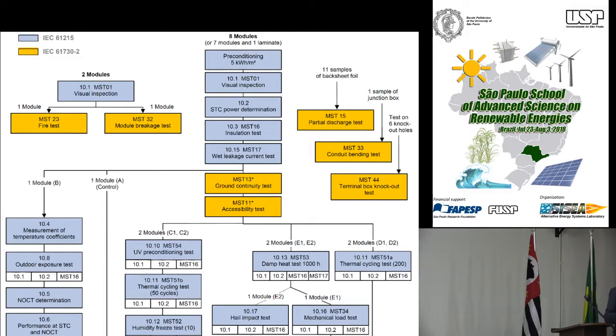That means we apply an irradiance value of 1000 watt per square meter on the module perpendicular. We make sure that the operation temperature of the module is at 25 degrees Celsius and the spectrum is equivalent to AM 1.5. And then we measure the power output in the maximum power point. And this we can perform, and then we check it against the actual labeling, for example.